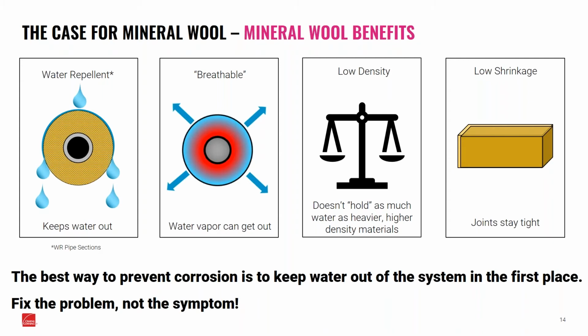And then finally, mineral wool has low shrinkage. The advantage to that is as you heat it up, those joints don't shrink and you don't create these gaps where moisture can actually go in and bypass the insulation. But again, the best way to prevent corrosion is to keep water out of the system in the first place. And again, we want to fix the problem and not the symptom.